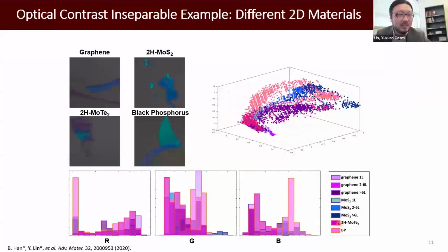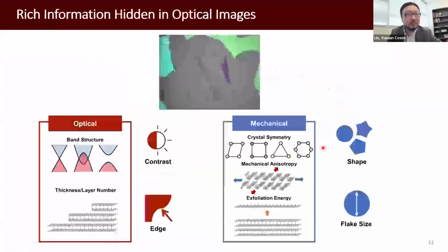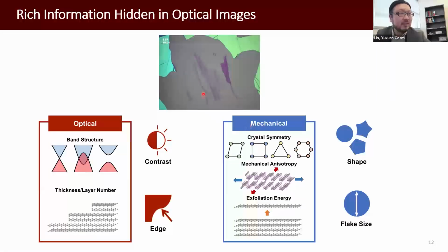Different colors mean different materials in the RGB space. You can see there's a significant overlap between different materials if we just use the RGB, the optical contrast information. But if you think about the entire process, we do mechanical exfoliation. For the optical information, so far people only use the contrast, but for the edges, there may be some subtle features we can use, especially the shape of those flakes. They are very related to the mechanical properties because of the exfoliation.